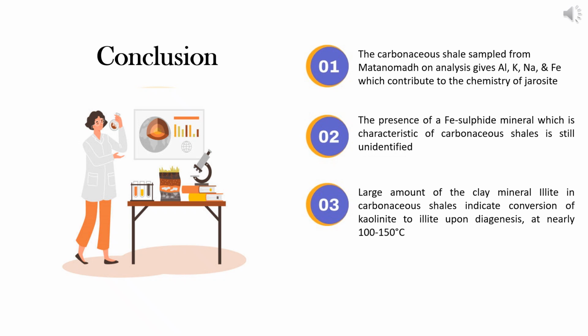1. The carbonaceous shale sampled from Matanomadh on analysis gives aluminum, potassium, sodium, and iron, which contribute to the chemistry of jarosite. These elements come from the chemistry of minerals like illite, kaolinite, and from the lower stratigraphic rocks such as laterites and basalts. It can be said that illite, kaolinite, and montmorillonite have originated from the chemical alteration of the lateritic layer of the Matanomadh formation.